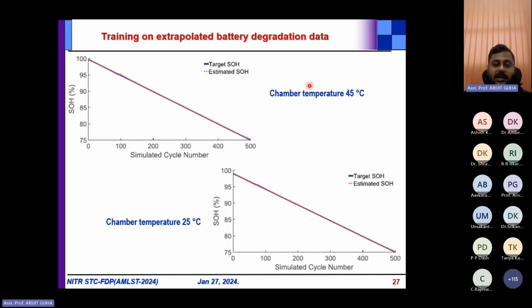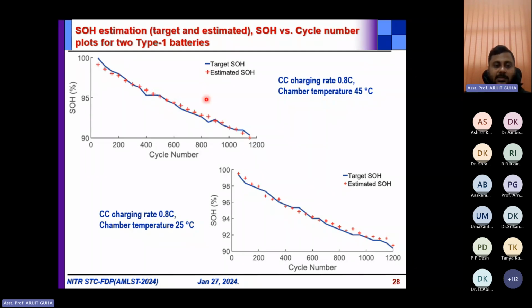Here, as I showed before, we have tested two different temperatures, one is 45 degree, one is 25 degree. This is the state of health versus cycle number plot. Here we have shown the target SOH, which is computed based on the probe cycle test and is considered as the reference, and the estimated SOH, which is computed based on the artificial neural network, and you can see that it is matching quite well. When the temperature has been changed to 25 degree, this is the outcome. So here the state of health, target and estimate, have both been compared.